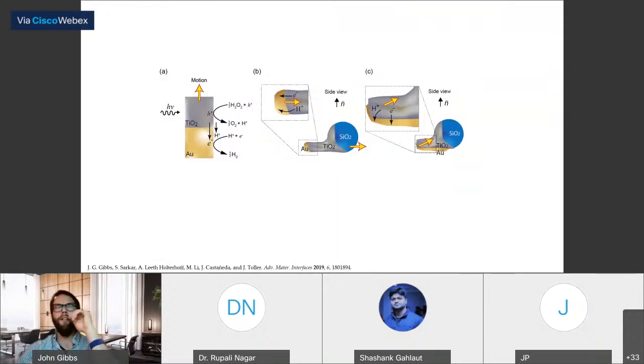However, if we want to look a little bit at the details of what's going on here, again, we have this interface. When we have a UV photon come in, we have this transition from, again, the valence band to the conduction band. But if we have this interface between the two materials, we actually get an electric field that builds up between them. And so what this does is the interface actually promotes the separation of the charges. So it enhances the photocatalytic activity. And depending upon which direction the charges are moving through the interface will actually dictate the direction that the fluid is going to respond to that movement of charges. So if the gold is located in different points of the structure, then you can actually get the fluid flow over the particle to go different directions. And so in that case, what you can do is you can tune the motion, hopefully.